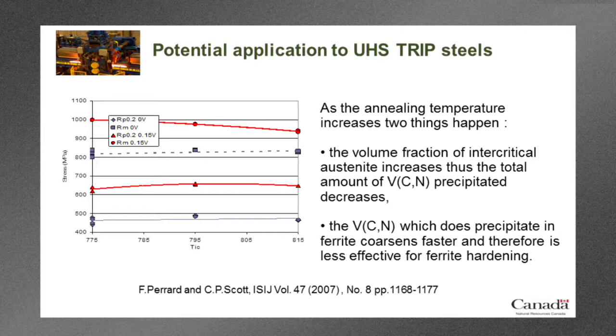Well, it's actually fairly simple. There are two things that happen as we go from this temperature up to this temperature here. First one, the volume fraction of intercritical austenite will increase. So the total amount of vanadium carbonitride precipitated will naturally decrease because of this dissolution effect in the austenite phase, which is more prevalent at the higher temperatures.